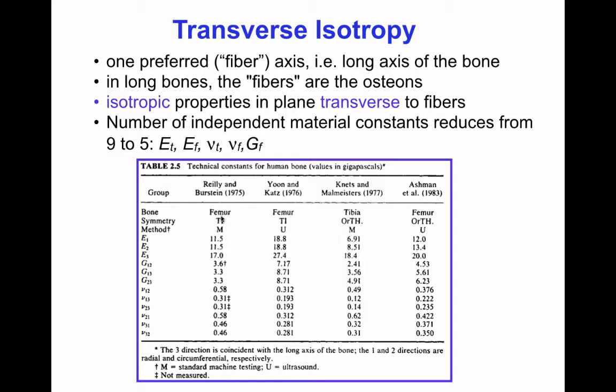For studies of the human femur, E1 and E2 are assumed to be the same, so the main difference is with E3. Bone is more accurately orthotropic, but the major directional difference is between the long axis and the other two directions, so transverse isotropy is also a common approximation. The measurement method matters: M stands for machine (uniaxial tensile testing), while U stands for ultrasound. Depending on the technique used, different measurements in real materials can be obtained.